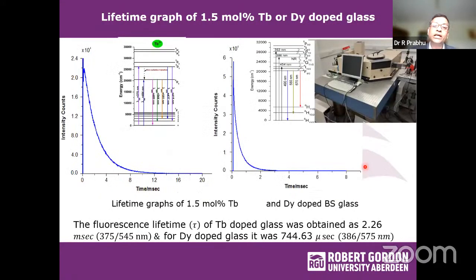In addition to this sharp emission, the spectral lifetime of these glasses can be of the order of milliseconds to microseconds. In the case of terbium, you can see the lifetime is around 2.26 milliseconds. That's for an excitation around 375 nanometers and emission around 545. And similarly for a dysprosium doped glass, the lifetime is around 744 microseconds. That's for 386 nanometers and emission around 575 here.